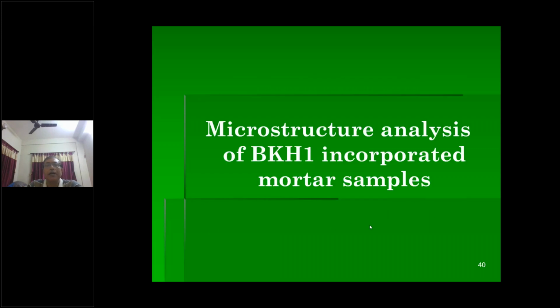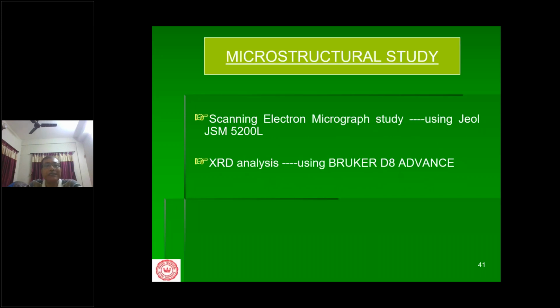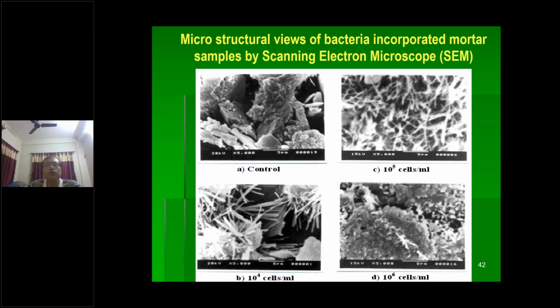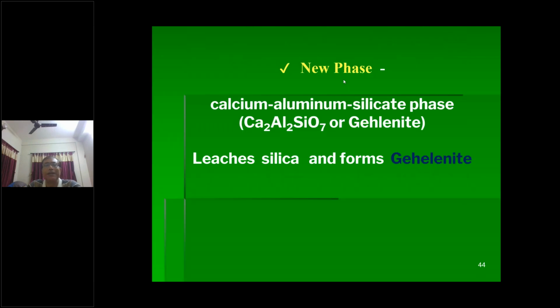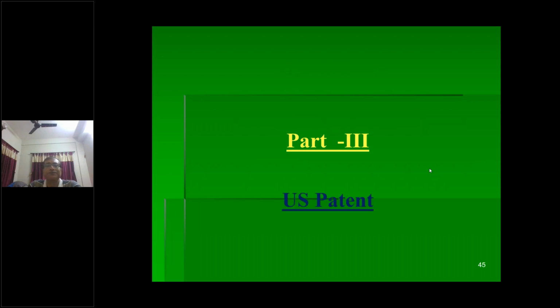FJ177512. We have also done microstructure analysis of BKH1-incorporated mortar samples using a scanning electron microscope and also the XRD analysis. Based on this, we found that a new phase has been developed within this matrix, a calcium aluminum silicate phase, which is named gehlenite. Basically, this bacteria leaches the silica and forms this gehlenite compound.